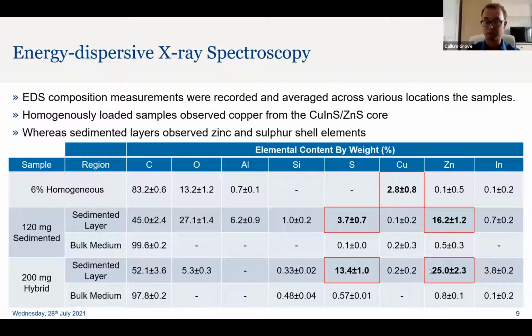But then the hybrid sample down below was slightly better in terms of conduction, and so we ended up seeing more in the sedimented layers. So this is an average recording for the sedimented layers. Despite there being more quantum dots in the sedimented layers of the sedimented batch, we saw more in the hybrid because the sample itself was more conducting and therefore produced better results.